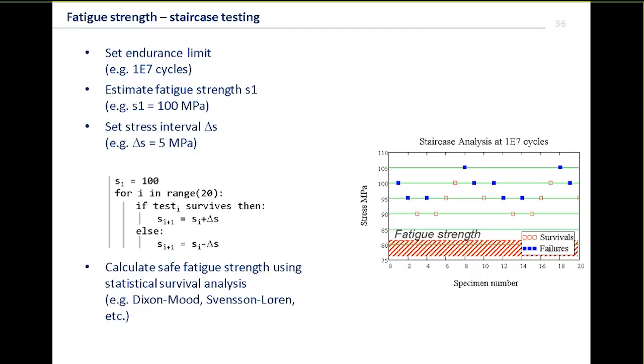Then, based on our SN analysis, we can estimate what we think that fatigue strength is going to be. In this case, I'm going to use, say, 100 megapascals, as it's a nice round number, just as an example. We also need to set our precision interval, delta S. In this case, a resolution of 5 megapascals is probably fine. And the way that we proceed is this.